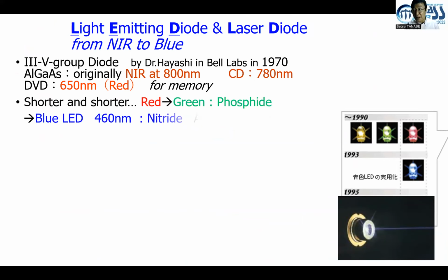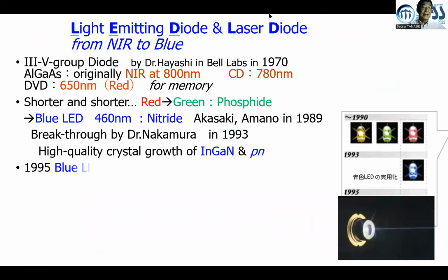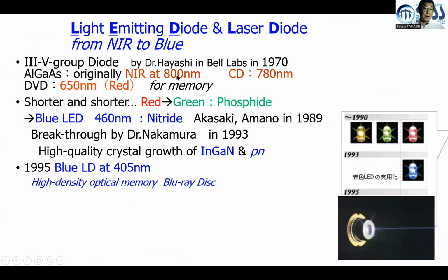That was IYL 2015. After the development of near-infrared and red phosphide lasers and green LEDs, the nitride blue LED was developed. The initiator was Professor Akasaki of Nagoya University. Amano was an undergraduate student and then a PhD student. Following that, Dr. Nakamura developed much higher quality crystal growth by CVD. And finally, indium gallium nitride and a PN junction were achieved. He also achieved lasing.